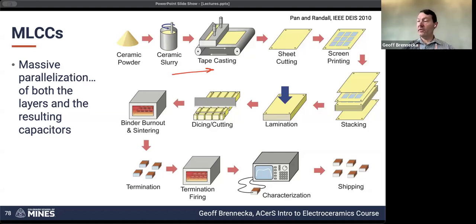Regardless of which approach you use, you end up making sheets out of this tape. So this tape still contains a lot of binder in it. And we'll screen print on electrodes. So if we think back to each one of those individual layers in the cartoon that I drew on the last slide, the gray electrodes were offset and stacked. That's just what we're printing here, as we're printing up each layer of that and then stacking them on top of one another. So they have to be aligned just right so that you get one layer here and the other layer there with maximum overlap, but not shorting.